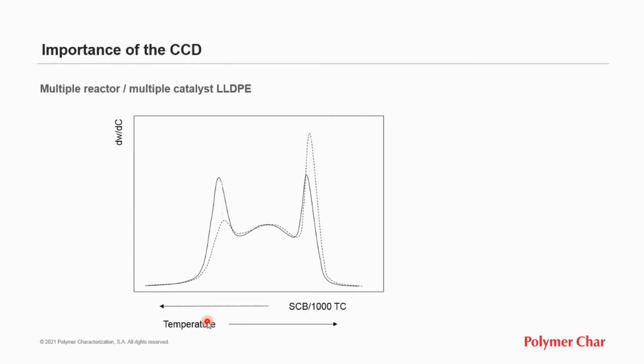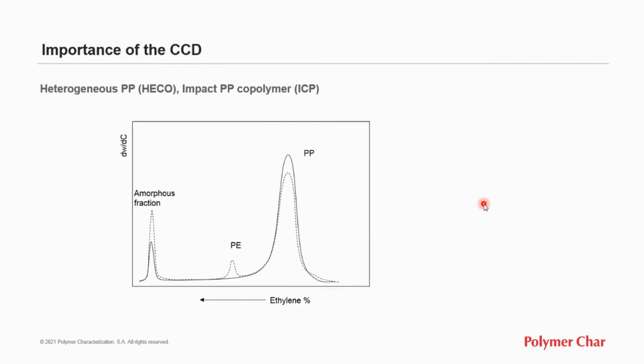Here, in this example, we see the case of a multiple reactor LLDPE, in which there are several degrees of freedom in product design by playing with the catalyst or process conditions, varying the relative fraction of each component, or also varying the amount of comonomer added. So the temperature would shift or the shape of the distribution would change. However, all those features are reflected very clearly in the chemical composition distribution, while in the molar mass distribution they have a very small impact. So in this case, separation by chemical composition is required even more than by molar mass.